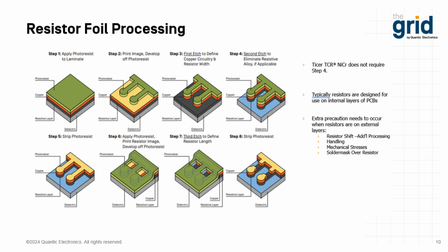And that's the beauty of this system: the alkaline etch, which is typically your outer layer etching solution for most circuit board shops, will remove the copper selectively, but not touch the resistor material. And so once that's done, we will strip off the photoresist, and now we have the resistors exposed, and our patterns are done. And then you would go to your traditional circuit board processing. First you do your electrical test, then you would do your oxide process or oxide alternative, and then go into your lamination process and go from there. So from that point on, it's like a traditional circuit board operation.